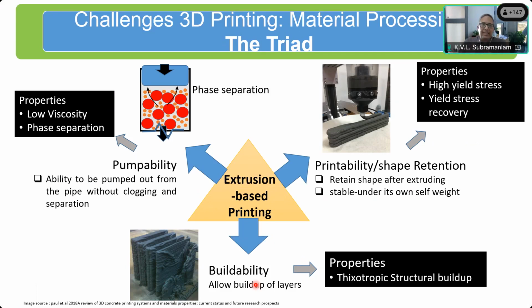So not only does it have to be pumpable, it has to have the shape retention. As it's coming out of the nozzle, it has to keep the shape, and it has to allow stacking of multiple layers. And all of this is happening in a matter of seconds to minutes. So it's not like concrete is setting. It is while the concrete is still fresh that I have to allow this buildability. So these are extreme challenges in terms of material. I really have to engineer the material, and that's where most of our effort has gone into, is into producing these mixes that can be printed, which meet this troika of pumpability, printability, and shape retention and buildability.